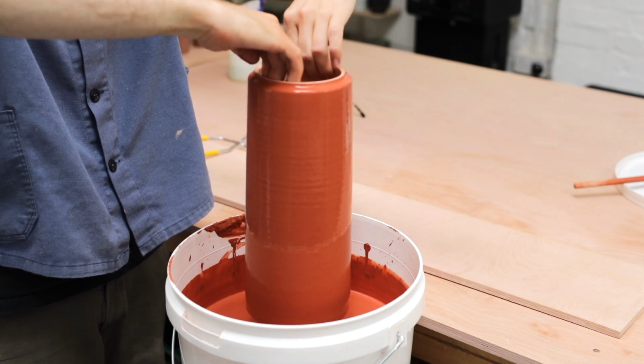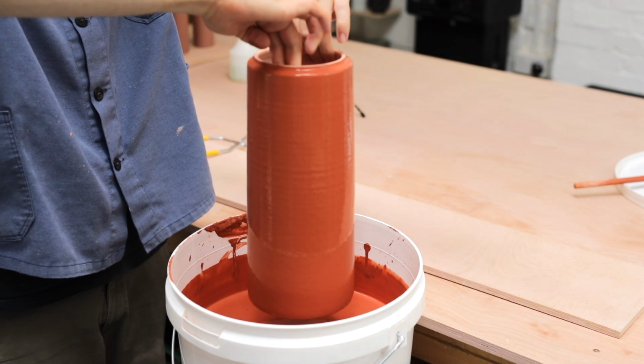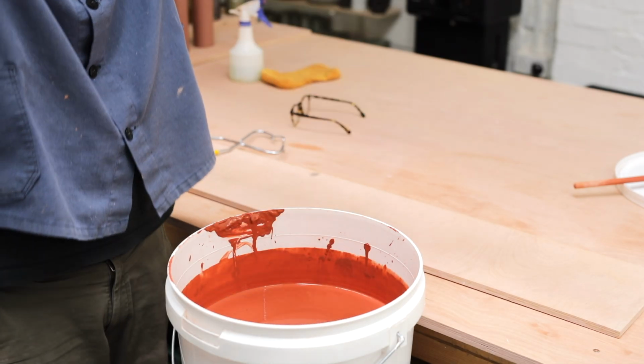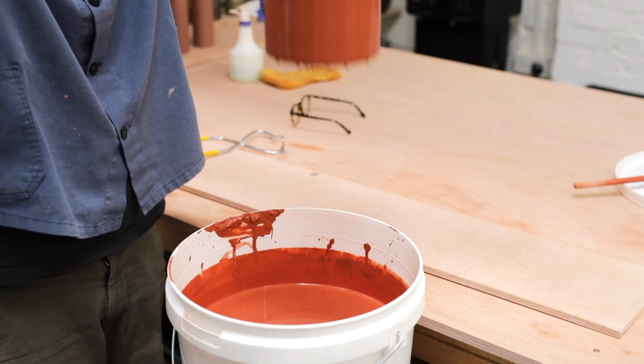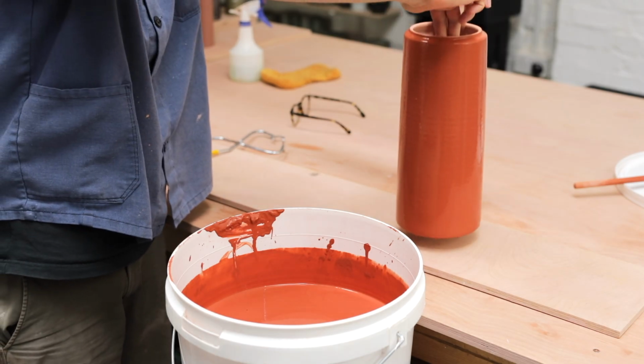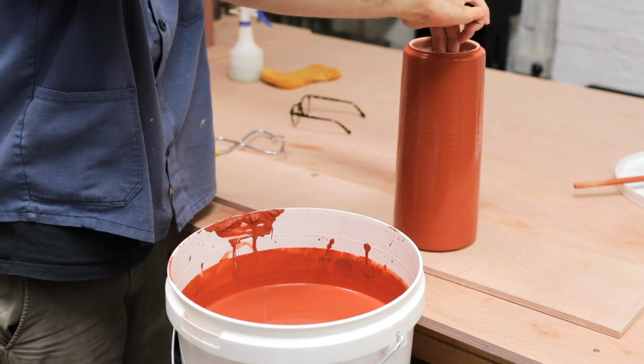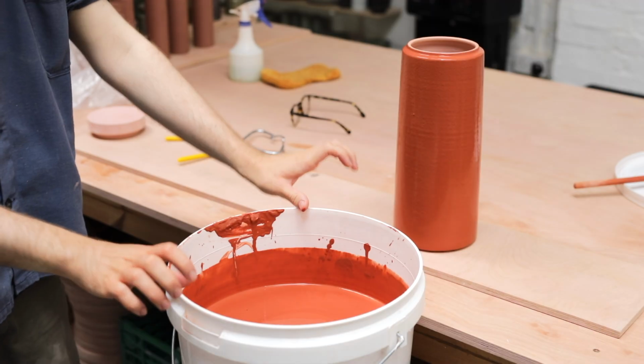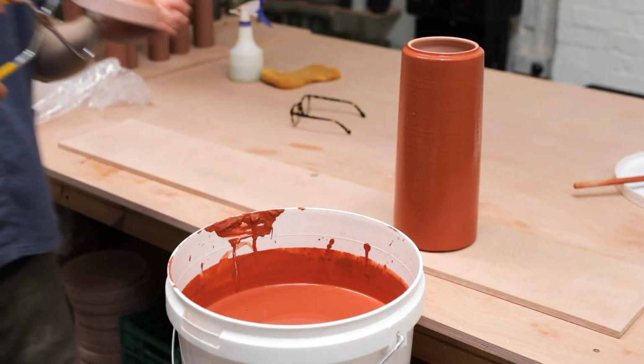This is a feldspathic crackle glaze, which contains lots of feldspar, nepheline syenite, talc, some whiting, some frit, and red iron oxide, and it's this which gives the glaze its red colour at this stage, but it's also this that will make the glaze turn green once reduction fired in the gas kiln.